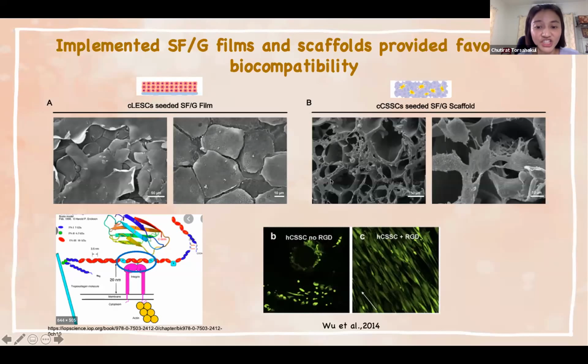Cell adhesion is influenced by the RGD sequence. Because in my study I used gelatin in the scaffold, gelatin provides a lot of RGD sequences. And in this study, the result compares the cells on the RGD scaffold and the cells on a scaffold without RGD. We can observe in this picture that the cells on the RGD scaffold can adhere better than the cells on the scaffold without RGD.